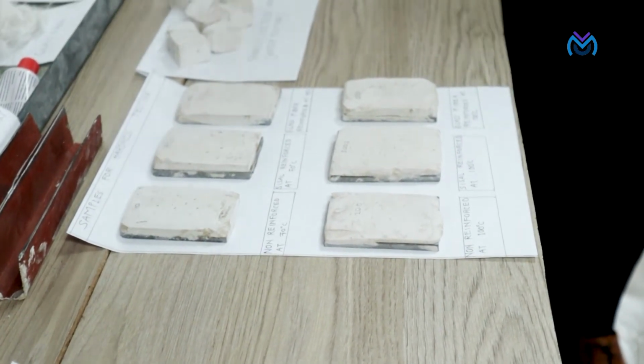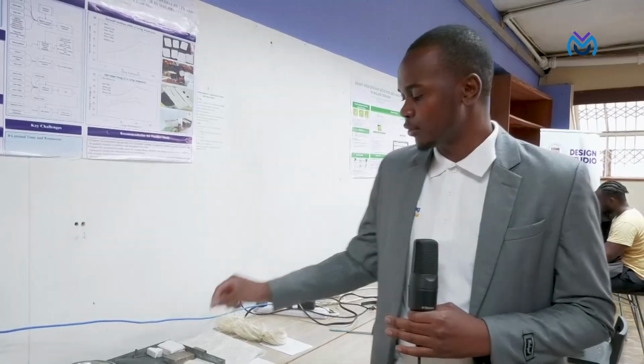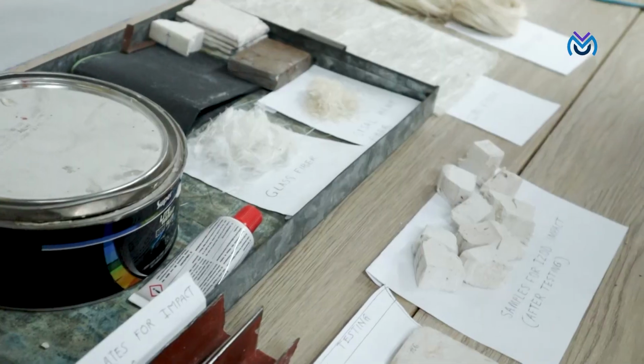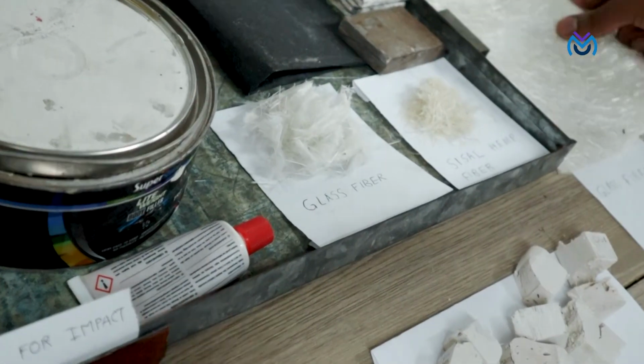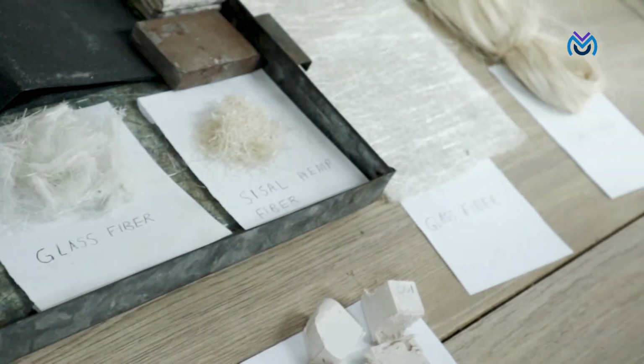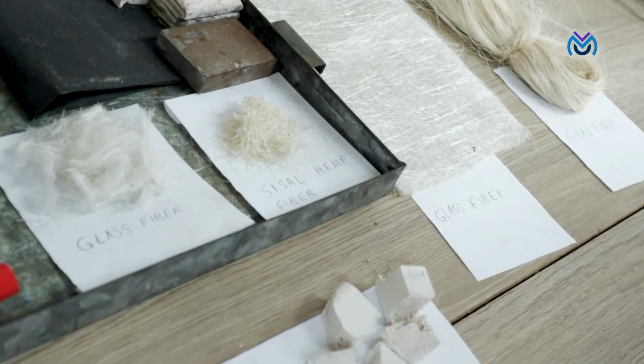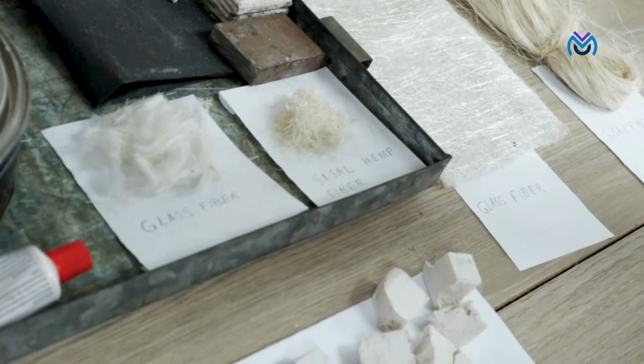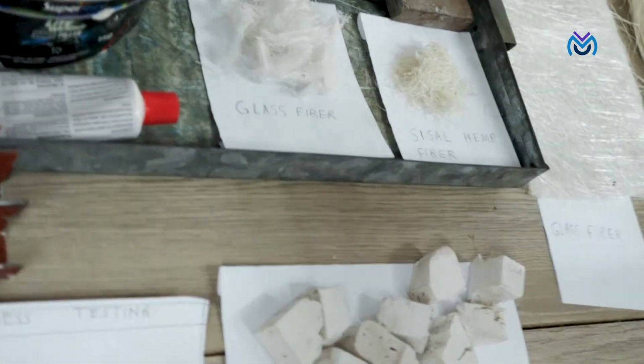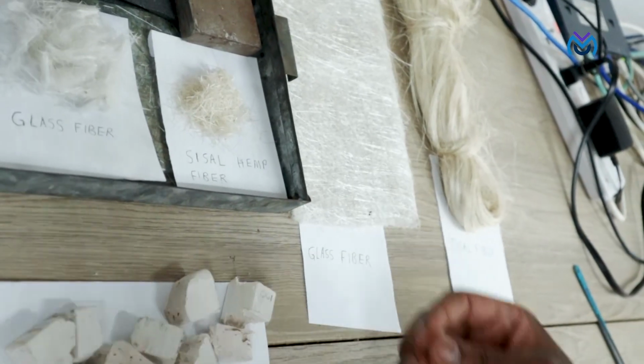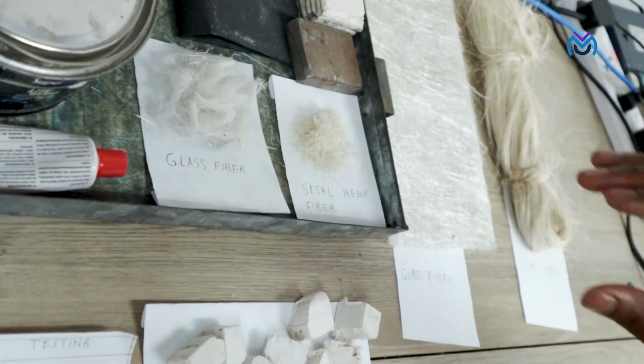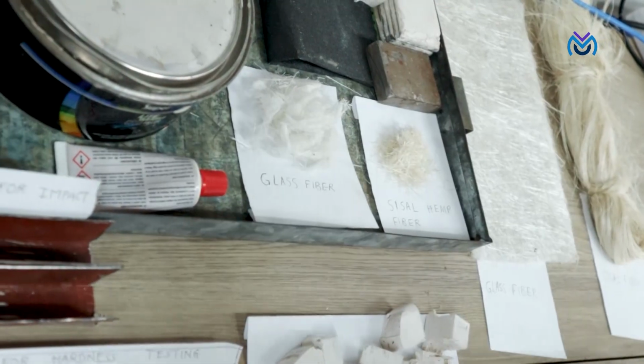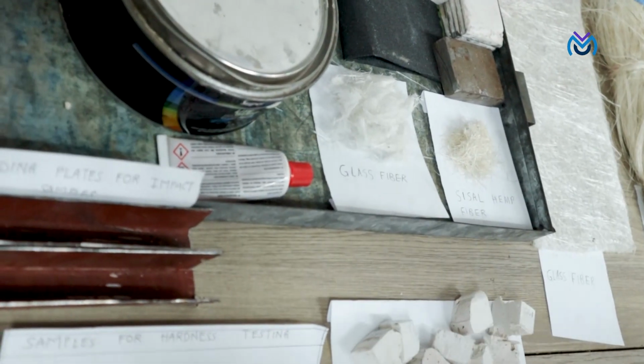So there's a solution on that where the industry uses glass fiber to reinforce it. But glass fiber is a synthetic fiber. Here's the glass fiber before it was prepared. Then we decided to use a natural fiber, which is sisal fiber, to replace the glass fiber. Here's the sisal fiber. We crushed it into small particles for easy mixing with the body filler to reinforce it to prevent it from cracking.